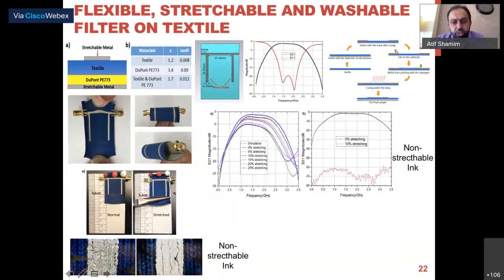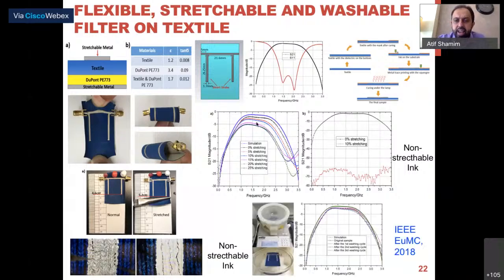We also did a washing experiment on it. We had a dielectric coating on it again. After a few washes, we tested it again, and it was working fine. Which means that you could actually have these electronics with this coating, wash them, and they are still expected to work.